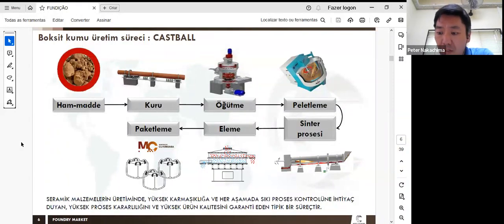After milling, we transfer the powder to the pelletizers. Using these pelletizers, we add water and additives to the raw material, and the movement of the vat and the internal tool produces the spheres. So during this process, we make the spherical shape of the Castball, and we also make the primary size of the product. So after pelletizing, we have the sintering process. We have rotary kilns here, where the temperature goes over 1400 °C to increase the density, reducing the porosity of the spheres, and consequently increasing the mechanical strength of the product. In this stage, we obtain the mineralogical phase of the Castball.